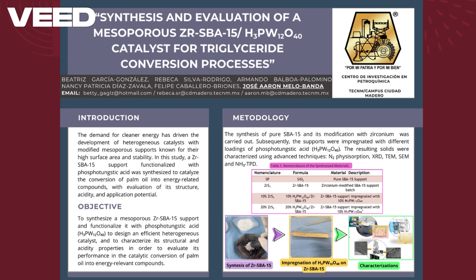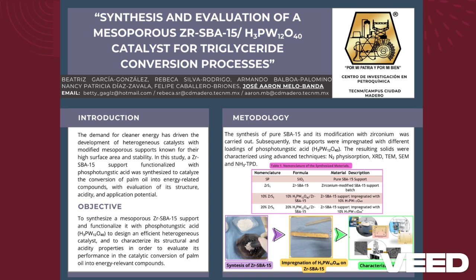Methodology. First, pure SBA-15 was synthesized and subsequently modified by incorporating zirconium into its structure. The supports were then impregnated with different loadings of phosphotungstic acid. The resulting materials were characterized by nitrogen sorption for surface area and pore analysis, X-ray diffraction to confirm the ordered mesostructure, transmission electron microscopy and scanning electron microscopy to observe the morphology, and temperature-programmed ammonia desorption to determine acidity. And, as we can see, Table 1 presents the nomenclature of the synthesized materials to facilitate their identification, along with their formula and a brief description of each.